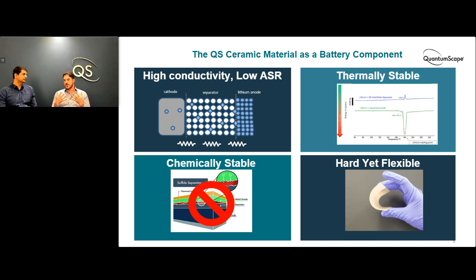So one of the big innovations at QuantumScape has been learning how to process our ceramic material in such a way that we can make it very thin without suffering any major deficiencies. And that's taken a long time to do, but now we have it under 100 microns. A lot of our separators we make today are somewhere between 20 to 40 microns thick. And you find that at that level of thickness, they now have a certain amount of flexibility. The other thing you need to achieve that is a low level of defectivity. Surface scratches, pits, flaws, any of those things would be stress concentrators. And when you start to flex a material that's full of defects, you'll instantly propagate a crack. So the fact that we can flex our material is a good indication that we've reached a low level of defectivity as well.